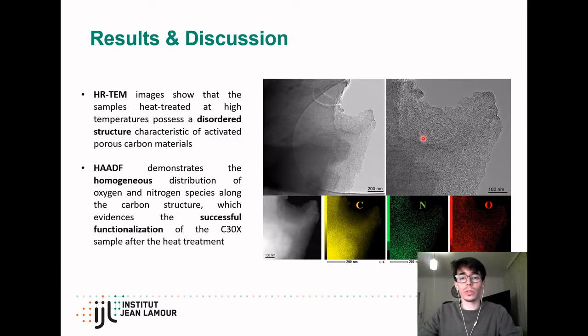The next slide shows the microscopy images, TEM images of the heat-treated samples, in which a disordered structure can be observed in the carbon material, which is characteristic of activated and porous carbons. Moreover, EDX mapping shows a homogeneous distribution of the nitrogen and also oxygen species along the carbon structure of the pyridine material, confirming the successful functionalization of this commercial carbon.